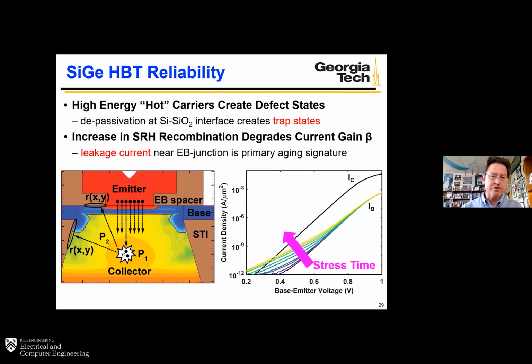The collector-base junction under sufficiently high collector-base voltage sees high field. We have a probability of impact ionizing the lattice in that high field, and those carriers have some probability of making it to the EB spacer oxide, which can produce trap states at that silicon-silicon dioxide interface by depassivating bonds. And that manifests itself in a recombination current, which you see on the right, which will degrade your base current over time. So if I'm in that stress regime, which is pretty easy to reach in modern devices, my base current is increasing as a function of stress time, and that of course is decreasing my current gain, which is typically undesirable. That's been the classical failure mechanism of bipolar transistors themselves, but it's much more nuanced than that. Very complicated problem.